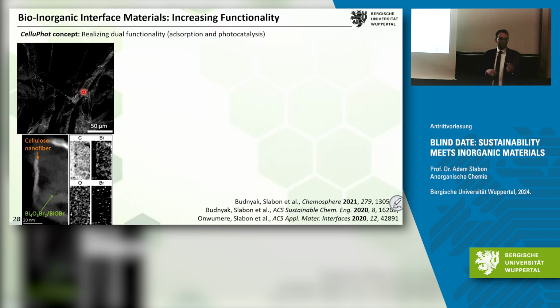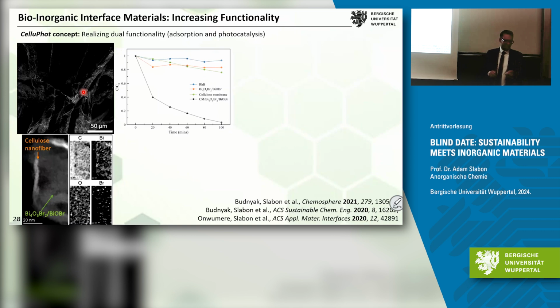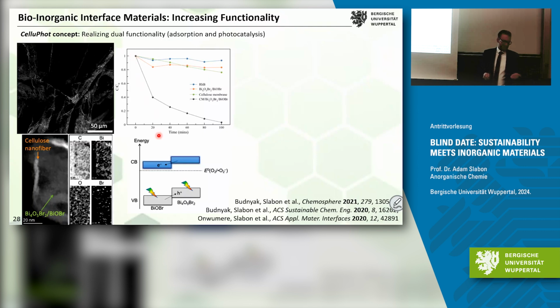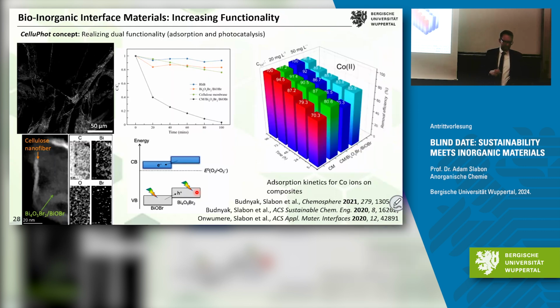If you have wastewater with organic pollutants, you can decompose them by photocatalysis. Here's rhodamine B. Because you have a semiconductor, you have the holes, and they can basically oxidize the organic matter. You also have the functional units of cellulose, and you can use them for adsorption of metal ions in the water.